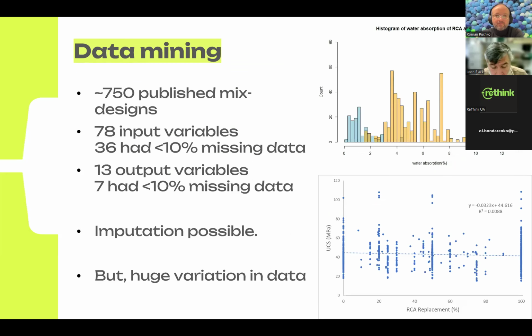But whilst we can do laboratory work to give this recycled aggregate an identity, to learn more about it, there are just realistically too many variables that can affect performance. The aggregate size and type are related to the water absorption capacity. As you get smaller aggregates, you get more adhered mortar and greater water absorption. You also get a change in the relative proportion of surface that is interfacial transition zone. And it just becomes incredibly complex. Whilst we can understand it conceptually, we don't really have the resources to look at every single variable.